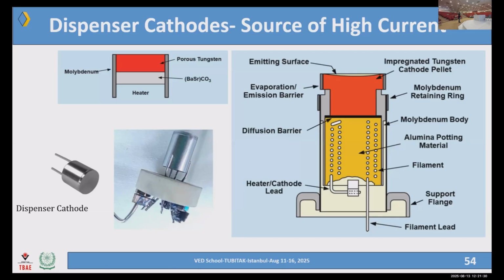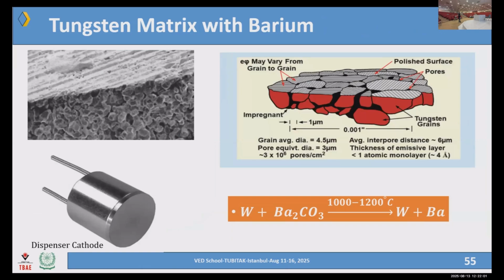So this is going to heat up. First, it's just like starting a diesel engine. The first few voltages will induce a cloud of everything coming out very fast. So this activation process, we call it activation, is the process where we convert the barium carbonate into free barium to be used here. I have written an equation here. This is pretty much the recipe, but the chemistry is at a sub-zero level in chemistry, so please don't ask questions. Barium oxide, barium carbonate, just to have a higher uniform heating, this is mixed with calcium carbonate and aluminum oxide, alumina, and the powdered form is then heated, and when it's subjected to tungsten, it is forming a monolayer here.